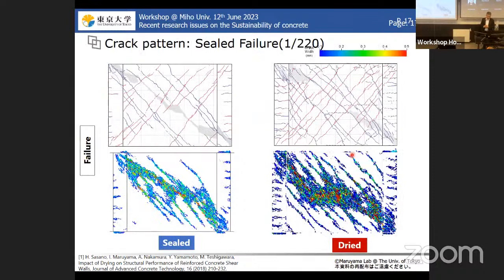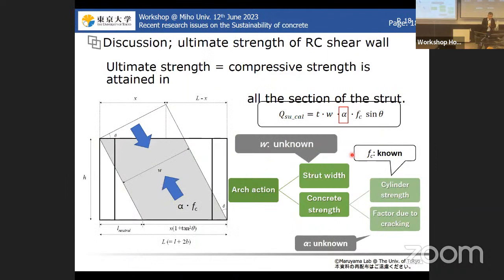And this is the comparison of the crack patterns of the experimental results and also the calculation results. And we see a large number of fine cracks and shear cracks as observed in the dried case. And this is not so important. What is important is how to calculate the ultimate strength of the shear wall affected by the drying.